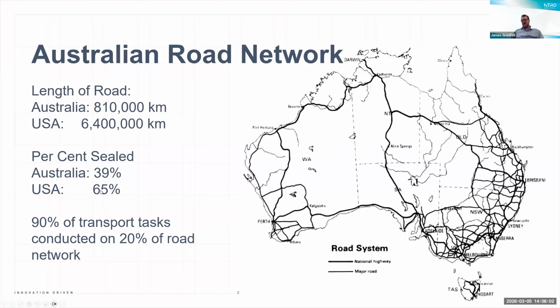The other thing is that we have a relatively small amount of the network that's actually sealed pavement. I think some of the numbers are around 90% of the pavements in Australia are granular pavements, either with or without sprayed seal. And so only around 10% of the network is full depth bound pavements, be that asphalt or concrete. The other interesting thing is around 90% of the transport tasks are undertaken on only 20% of the network. So big disparities in terms of traffic levels as well.